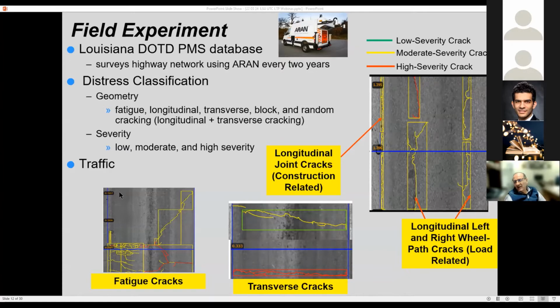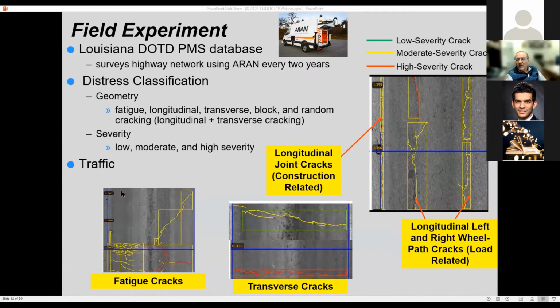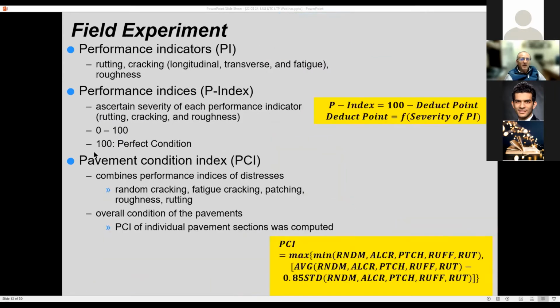It's got a lot of data mining because you've got to separate the distresses. It's collected every 1/10 of a mile. And also we wanted to separate, for example, the load associated cracking versus non-load associated, meaning the edge cracking and the longitudinal joints, because these are not really related to the performance of WMA.